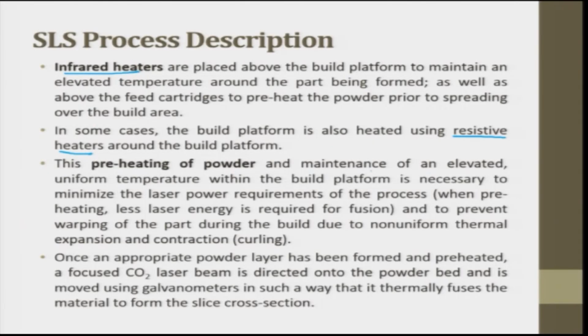This preheating of powder and maintaining it at an elevated uniform temperature within the build platform is necessary to minimize the laser power requirements for the process. Very important point. That is why we preheat the powder: to minimize the laser power requirements of the process and to prevent warping of the part during building due to non-uniform thermal expansion and contraction. So this is the other thing. It prevents warping; it is necessary to minimize power and prevent warping. These two are important points.